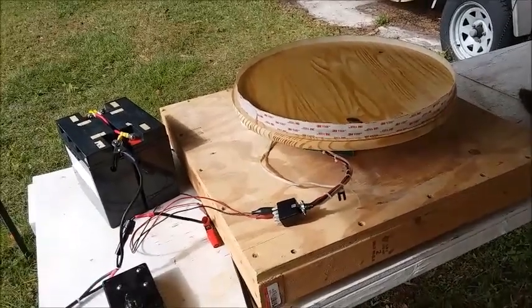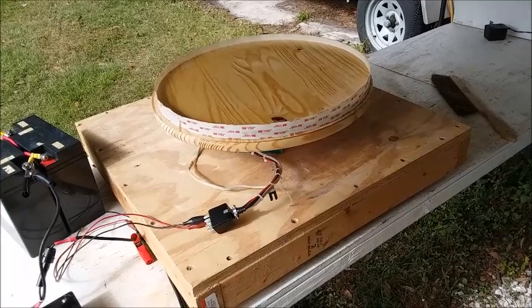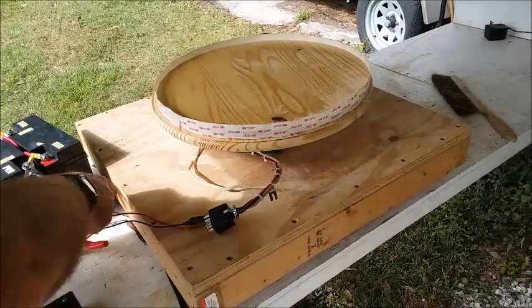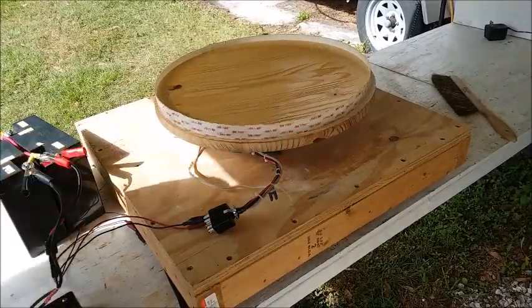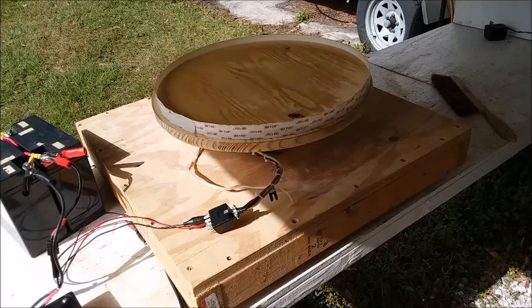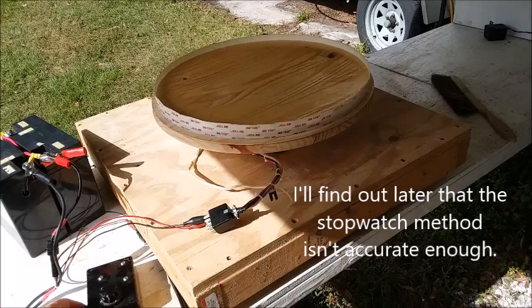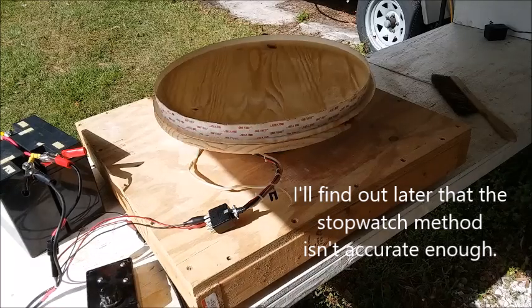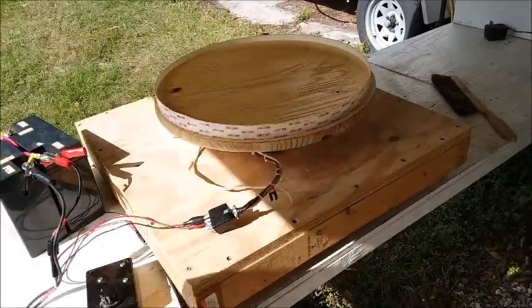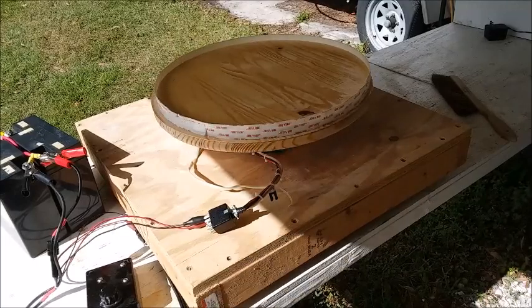What I think I'm going to do is pour some self-leveling bar top coating on it — about an eighth of an inch thick — and do it while the disc is spinning at the speed necessary to create the curve I want. This is an experiment. I used a stopwatch and timed it, and I've got my variable speed controller here with the turntable turning at just the speed I want. Centrifugal force should make the self-leveling epoxy coating form a parabola of the curve I want.